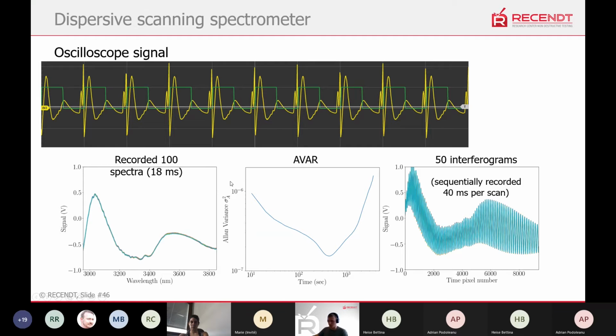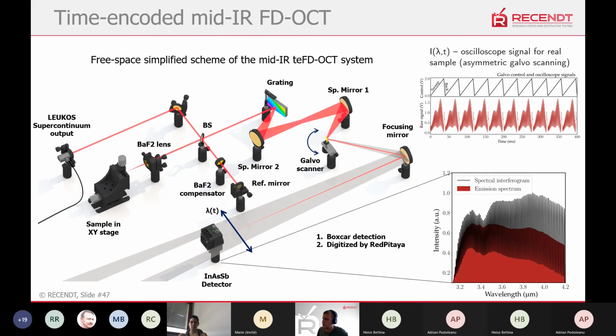One concern was the linearity and stability of this system, but actually it worked quite well. This is just 100 spectra recorded sequentially, at 18 milliseconds per spectrum. We can see that these spectra do not fluctuate a lot, and neither do the interferograms. So the phase is also stable here. Of course, maybe there is some jitter because of mechanical noise. It was stable, partly non-linear, but the non-linearity can be compensated numerically.